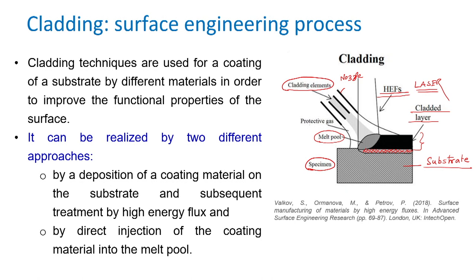So, this is the difference between laser surface cladding and laser surface alloying. In alloying, the entire molten material will be a different combination than the substrate material and deposition material. However, in the cladding, at the interface of the substrate and the deposition material, there would be a mixture occurring. Here we want to have the material properties of the cladded material over the surface, and the substrate material will also have its own material properties.